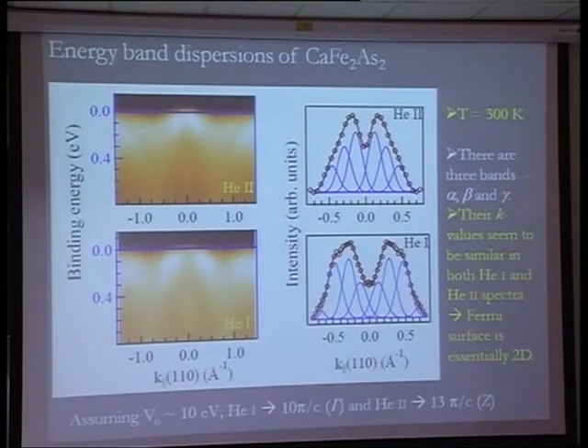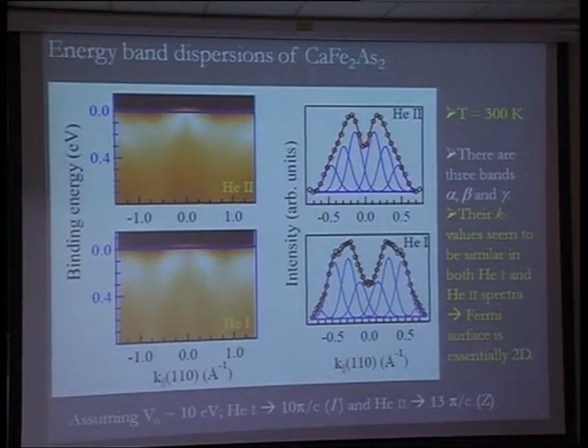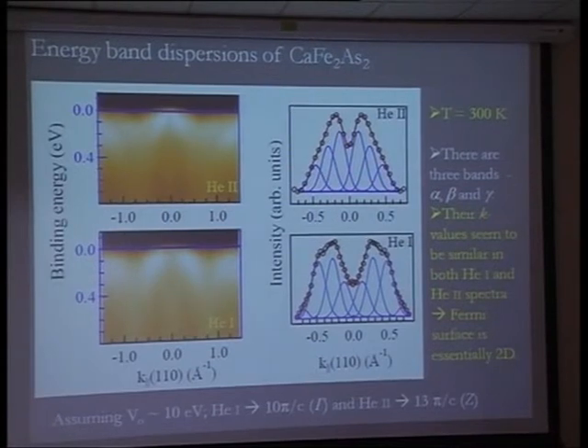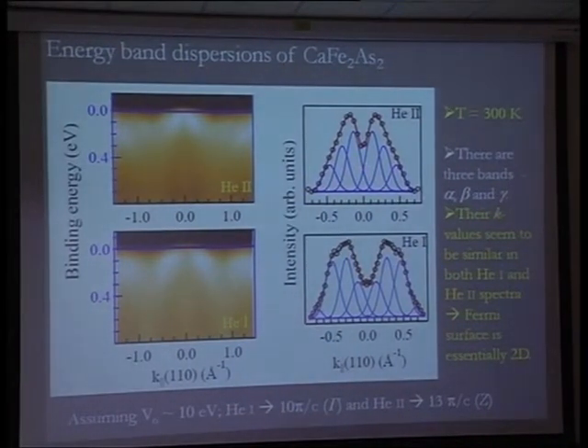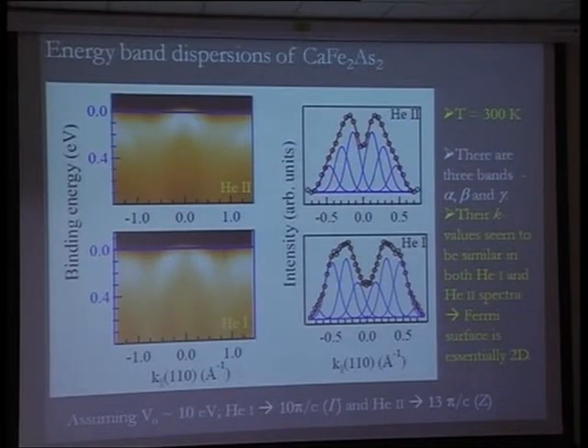Now look at our ARPES data. I have not drawn any line here, just to show the raw data. So here, if I plot the MDC, my momentum distribution curve, around 100 millivolt, you can see that these are all room temperature spectra, so the features may become a little broader compared to the low temperature spectra, which I'll show very quickly. So you can see that there are three bands, and the K value seems to be very similar in helium 1 and helium 2, but the intensity of these features is very different.